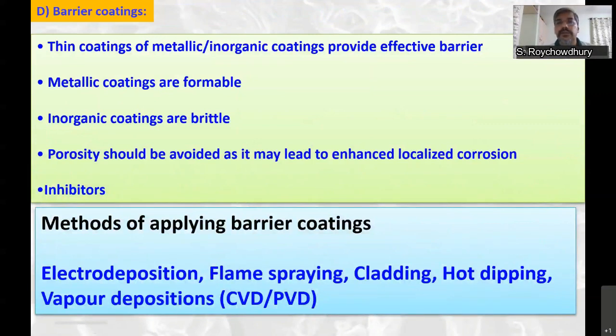Barrier coatings can be applied. Barrier coatings do not allow the environment to come in contact with the base metal and thus prevent corrosion. They can be thin coatings of metallic or inorganic nature. Metallic coatings are preferable because they are formable. If you bend the metal, the coating will also bend. It will not peel off. That is not so for inorganic coatings. With time, they become brittle and peel off easily, exposing the base metal, and corrosion will progress unabated. Porosity should be avoided in these coatings because if the base metal is locally exposed, it will lead to enhanced corrosion.